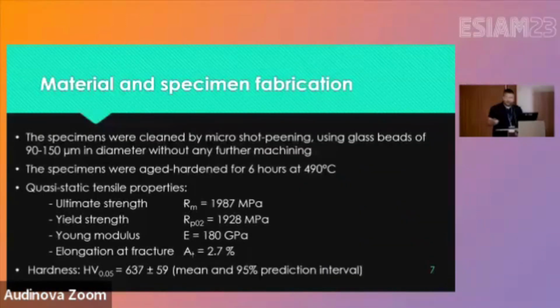The mechanical properties are as follows. It was age hardened for 6 hours at 490 degrees Celsius, then cooled in the oven for another 2 days, and this is what EOS recommends. Ultimate tensile strength is up to 2 gigapascals, yield strength very close, 1928, Young's modulus about 180 gigapascals, and the elongation after heat treatment. In the last presentation, it was 13%, 11 to 13 basically. Here it's 2.7. It gets much harder, with much less plasticity, and the hardness is roughly 640 HV.